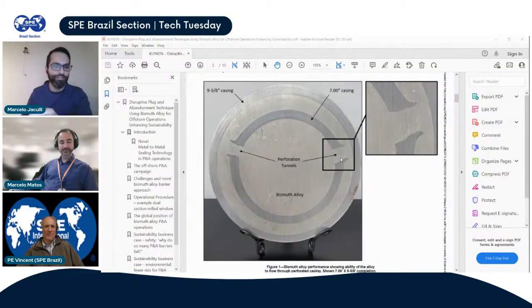They made this perforation within the inner casing, and then they poured the bismuth there, and you allow it to melt and fill the annulus behind the casing as well, the annulus B. But you could have cement there as well, so you could use this to remedy the cement behind the casing. It could be another application, regardless of whether you are replacing cement or even improving cement. So again, it's another tool in the box.